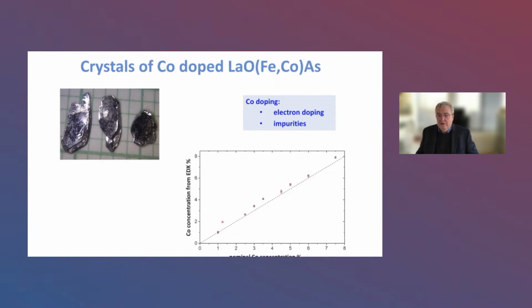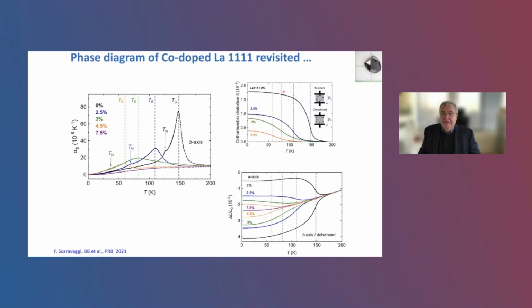So we have now a series of samples as a function of doping. We, of course, know that this is, let's say, not the best superconductivity or best superconductors which we expect, because on the one hand, cobalt doping is electron doping. We know that, of course, because cobalt has one d electron more than iron. On the other hand, it's an impurity, and I've shown you already how sensitive these unusual bad metals react to impurities. So therefore, we expect that superconductivity will be very bad in these systems. And that's also what we find at the end.